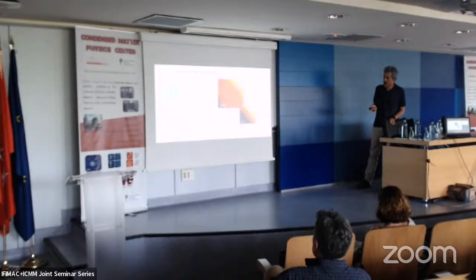Okay, we can now retract, and what we see is that this red curve here is the part where we are in contact, the part where we have the metallic contact. Here we can plot the thermal conductance as a function of the electrical conductance, and from the slope of this curve we get about 1.2 nanowatts per Kelvin per quantum. This is like double what we should have, because basically we have a contribution from this adsorbate layer. Okay, so we were happy with this result, but still.